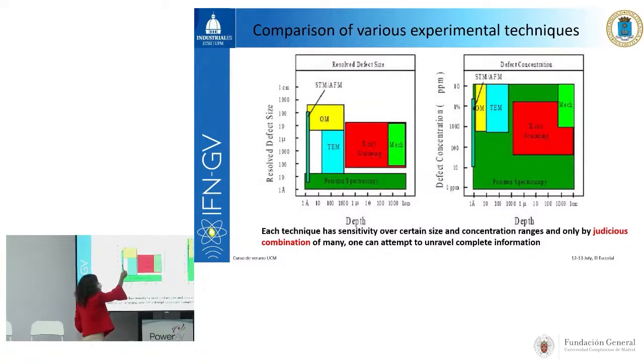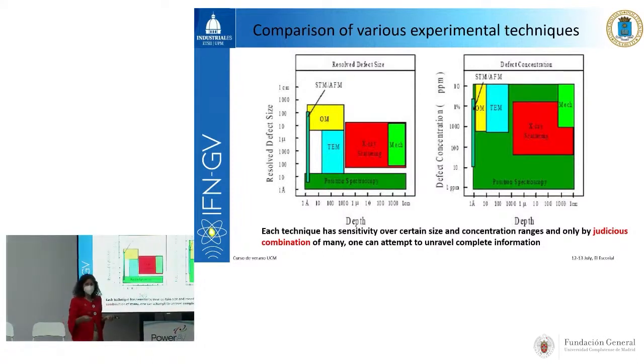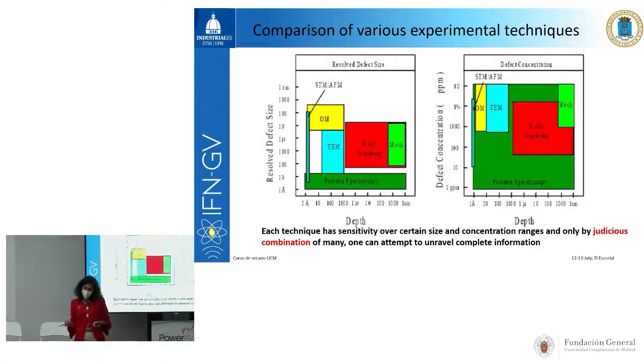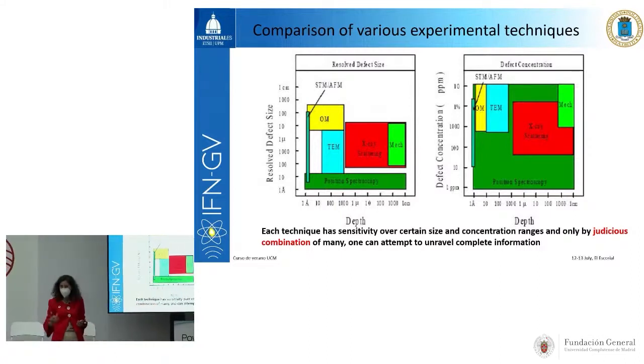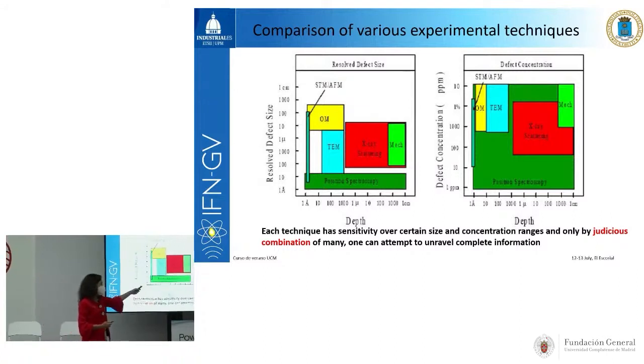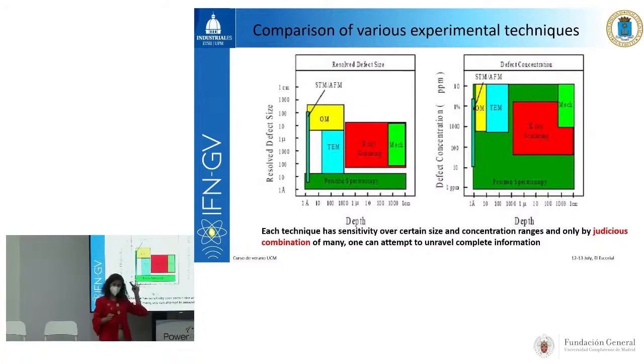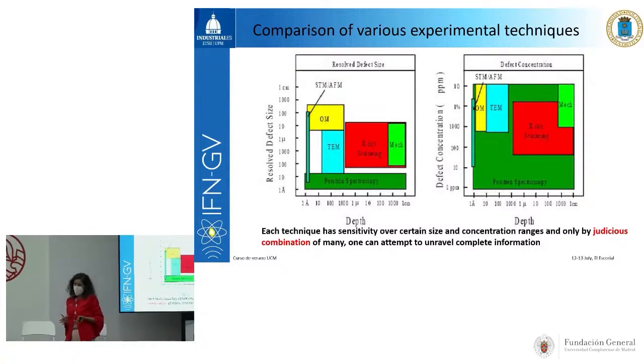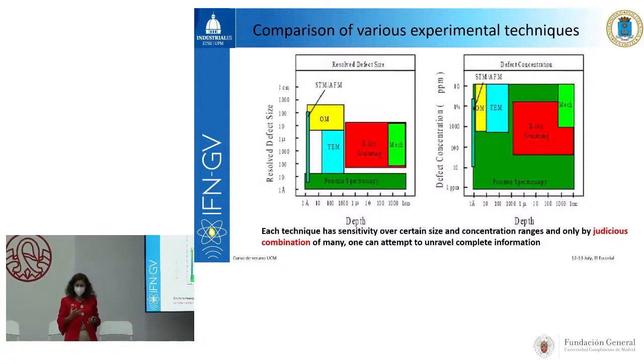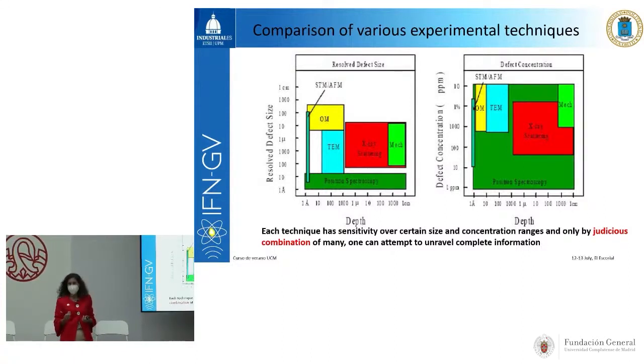Then, in between the resolution of optical microscopy and positron spectroscopy, we have scanning tunneling microscopy or atomic force microscopy if defects are located on the surface, or we may go, for example, to transmission electron microscopy or X-ray scattering if defects are located underneath the sample surface. This depends on the defect size, but we also have to consider what defect concentration is expected.